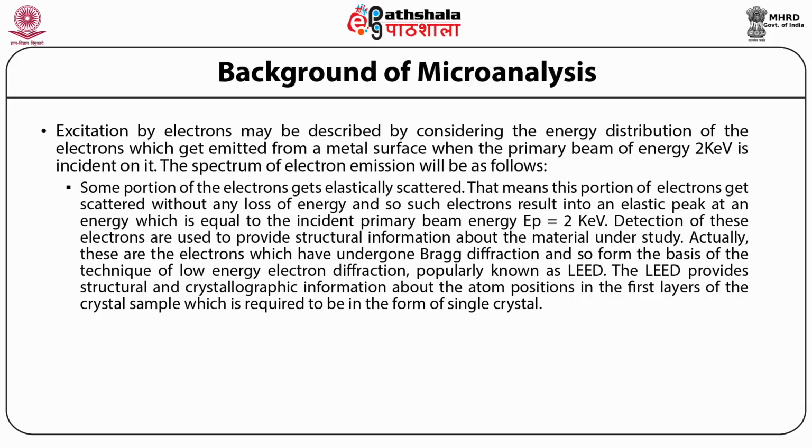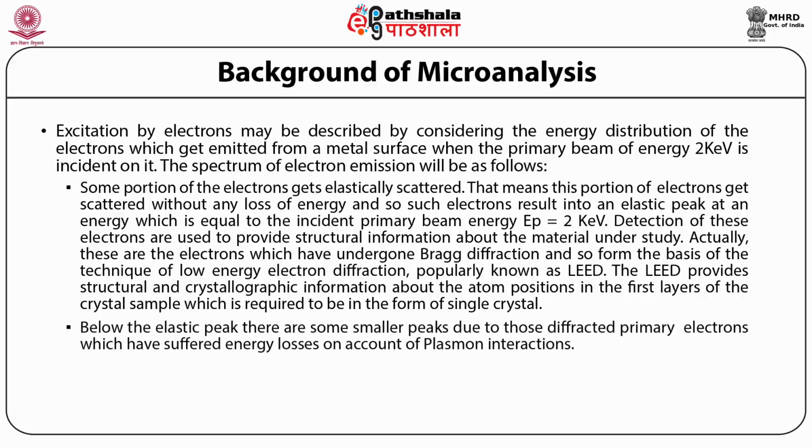LEED provides structural and crystallographic information about the atom positions in the first layers of the crystal sample, which is required to be in the form of single crystal. Number 2, below the elastic peak, there are some smaller peaks due to those diffracted primary electrons which have suffered energy losses on account of plasmon interactions.